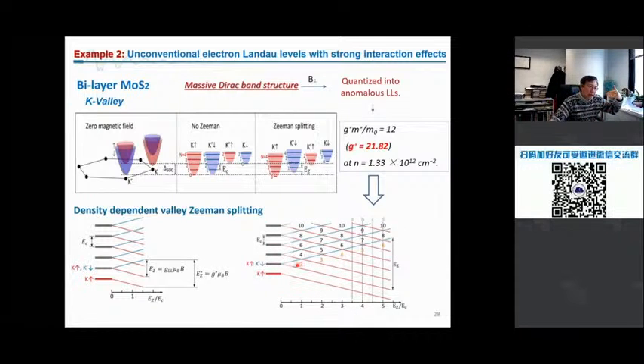It's quite similar, except this time it's not tilting, but the ratio of Zeeman energy and cyclotron energy that is carrier concentration dependent. So once we change this ratio, change N, we can measure the crossing points, the 4, 5, 6, and so on. And you will see blue and red is spin up, spin down, but from different valleys. At low filling factors, for example 1, 2, 3, it is just isospin, like ferromagnetic. Then in higher states, it is mixed spin up, spin down.